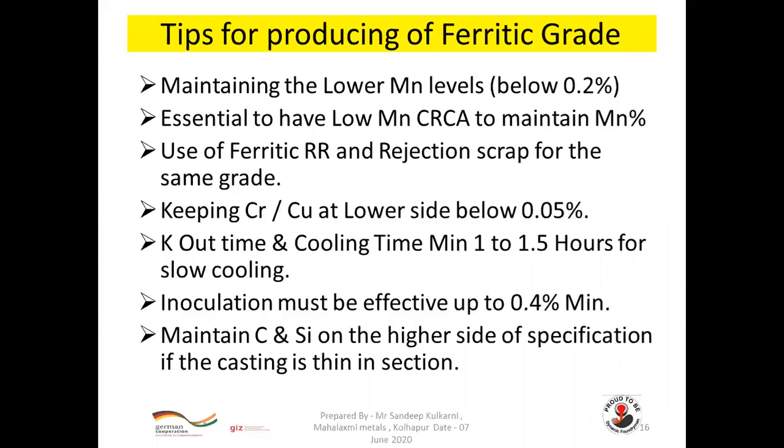Use of ferritic runner riser and rejection scrap for the same grade. That is, avoiding mix up of higher grade runner riser and rejection is essential. Keeping chromium or copper on the lowest side, that is below 0.05%. For that, you have to avoid any bath metal of heavy or higher grade. So you have to empty out the furnace before you start ferritic grade so that you are able to maintain your chromium and copper on the lower side.